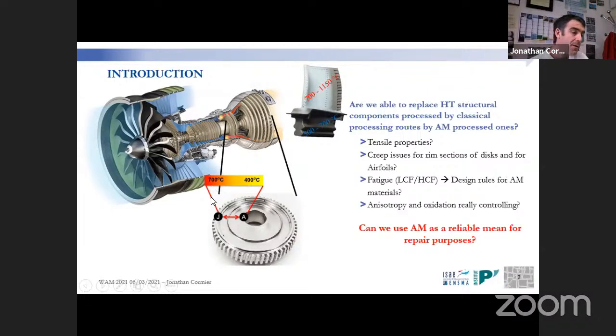So here you have the typical temperature during service of those components, ranging from 400 C in the bore sections up to 700 C for the rim sections. And regarding airfoils, especially HP sections, we are ranging from 500 to 700 for the blade roots, up to 1150 C at the blade tips. So the key questions are: are we able to replace those components conventionally manufactured, are we able to process them by additive manufacturing? And the subsequent questions are what would be the tensile properties, creep properties, fatigue properties, and the anisotropy and oxidation